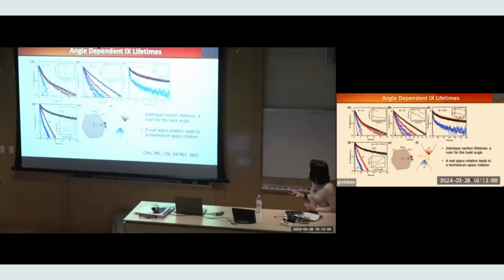Another thing that's interesting is the lifetime of these transitions changes with twist angle. You remember there were multiple peaks, right? When I look at different energy peaks, I find high energy peaks decay faster. That's one of our reasons to believe they're higher excited states. And also, as you twist the angle, 1, 2, 3, the lifetime gets much longer with the twist angle. What's going on? There's a simple explanation.